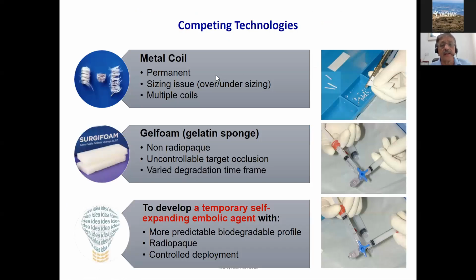Right now, there are embolic plugs available through the use of metal coils, but these are permanent. Gelatin sponges are also used, but unfortunately this is uncontrollable target occlusion, not predictable, very variable. The degradation is also quite variable because the collagen or gelatin is enzymatically degraded, so you cannot predict how long it'll take for them to degrade. So we wanted to develop a temporary self-expanding plug with a predictable biodegradable profile, which is also radio-opaque and can be deployed in such a fashion to completely occlude the target vessel.